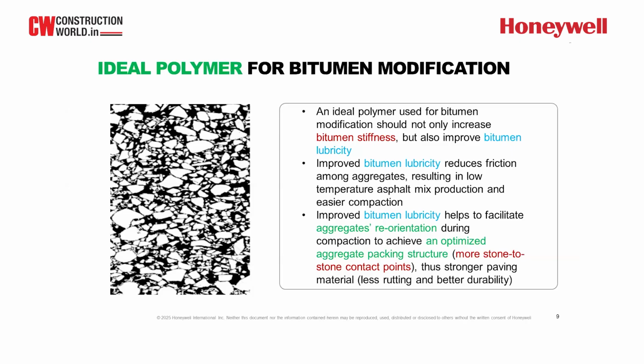With a polymer which can increase the bitumen lubricity, it will reduce the friction among the aggregate, right? So when you do the compaction, you can do it at a lower temperature, and you can potentially reduce the mixing process temperature at the plant to produce the aggregate mix. Also, with improved bitumen or PMB lubricity, it will help facilitate the reorientation of aggregate during the compaction to achieve an optimized aggregate packing structure. We will show you real images we took in the lab from the core sample, how Honeywell helps to optimize the aggregate packing structure, right?